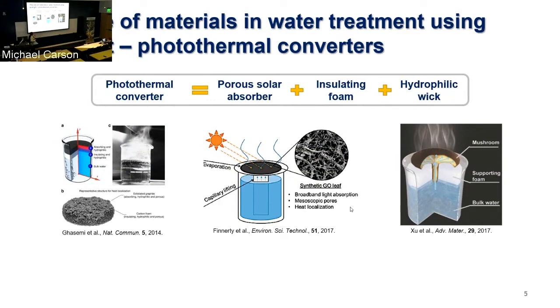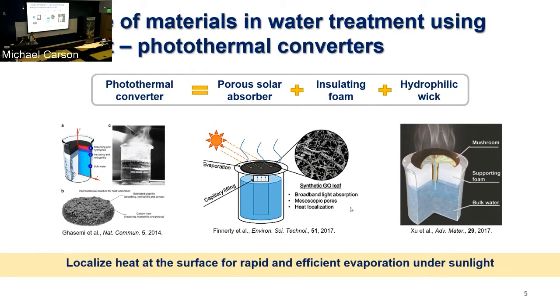A lot of the prototypes in the literature that I'm showing here are carbon-based foams, like I said, and in some cases there have also been some biologically inspired ones. This was a mushroom which went through a carbonization process to help it become a better solar absorber. And the water transport in the mushroom is naturally designed in a way that allows you to get this kind of photothermal wicking. It's a natural mushroom, yes. Just a regular mushroom which was carbonized to give it a very high solar absorption. So the idea here is that we really just want to localize the heat where we need it, which is where the evaporation is happening, rather than heating a large volume of the liquid itself.